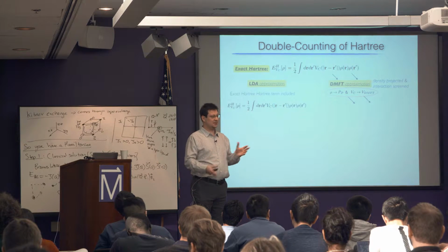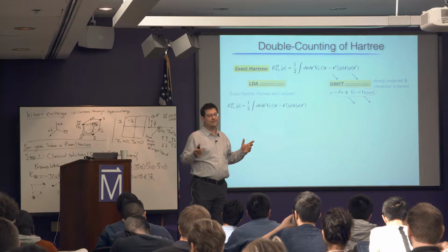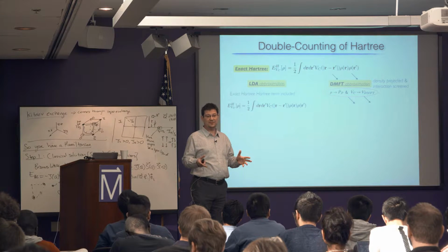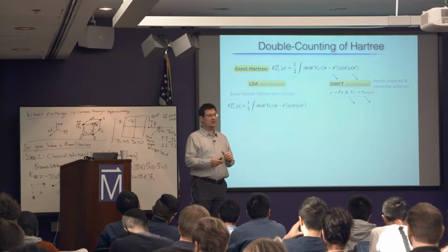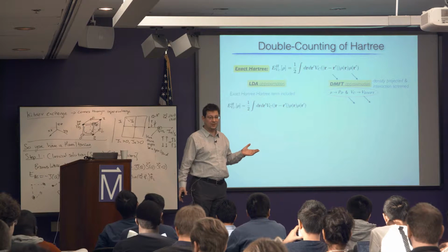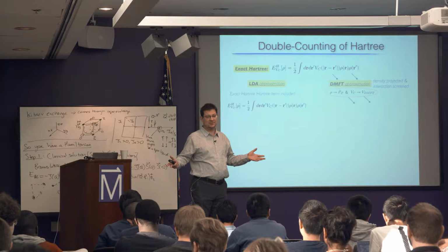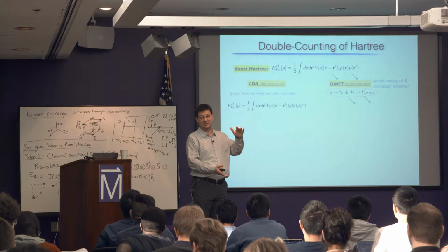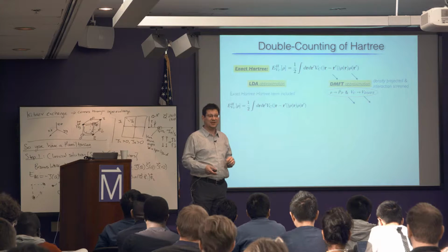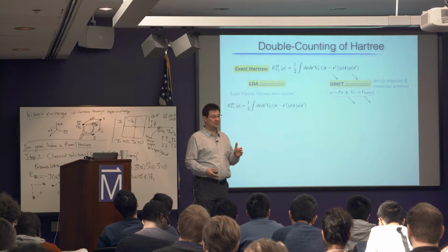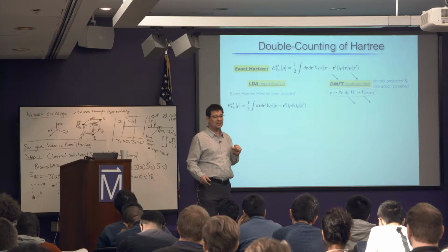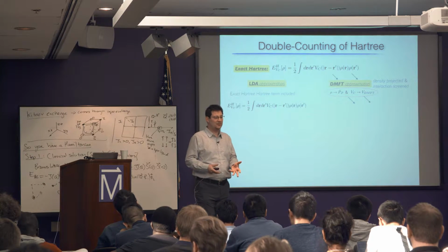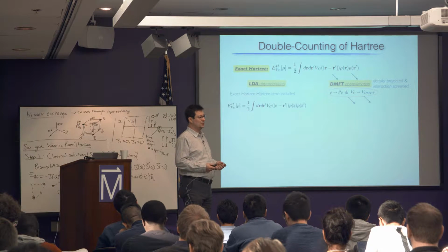Some people are saying, well, let's just take unscreened Coulomb repulsion. Well, you cannot do that. Why? Because we never take into account within DMFT all the degrees of freedom. So, of course, if we account for all the degrees of freedom, including core, then you don't need to screen the Coulomb repulsion. But we never do that. There is no way we can do that. I mean, right now we are usually taking one orbital or at most 2 orbitals, and all the rest is treated with mean field-like, isn't it? And all these rest of the states always screen the Coulomb interaction. Therefore, we cannot use unscreened Coulomb interaction.